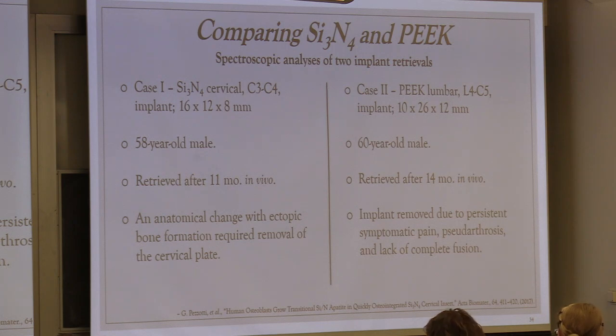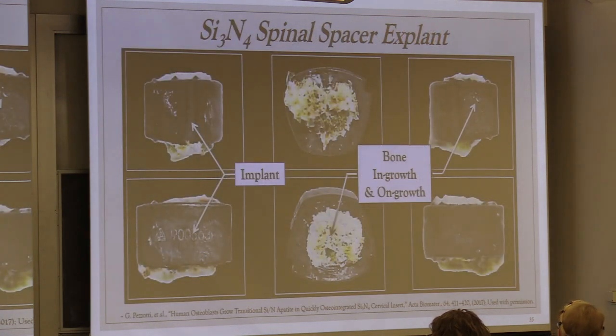And the other one actually was then a PEEK implant, which was in a little bit older individual, but comparative, and in there for 14 months. And this was because this particular individual had persistent pain, what's called pseudoarthrosis. The implant had not fused well enough. And so we got these two implants and did sectional analysis on them just to see what was going on, and then published about them.